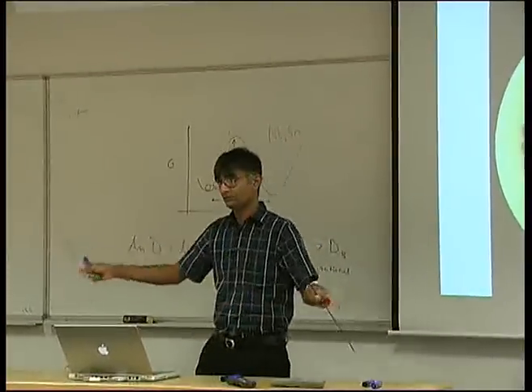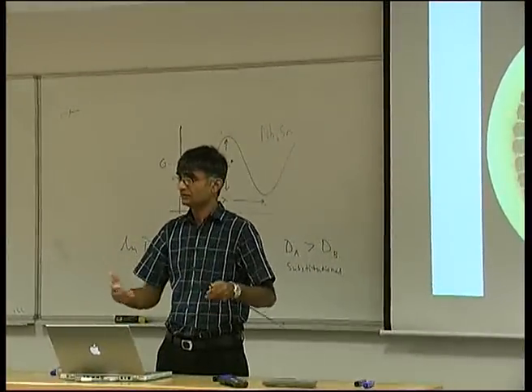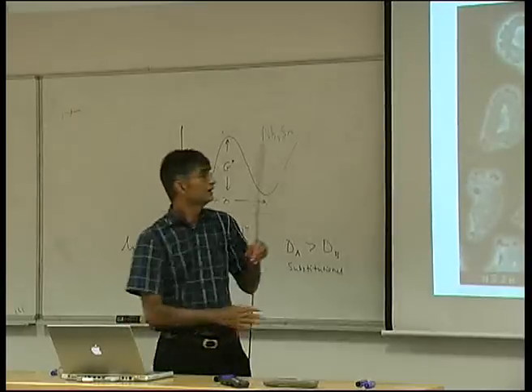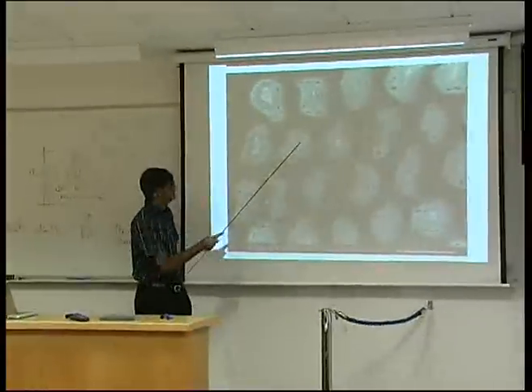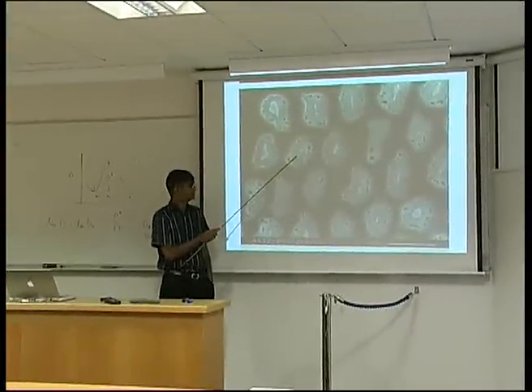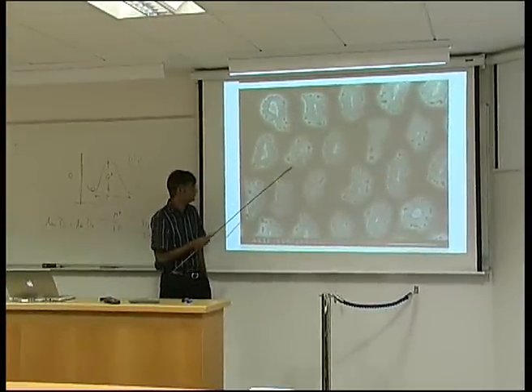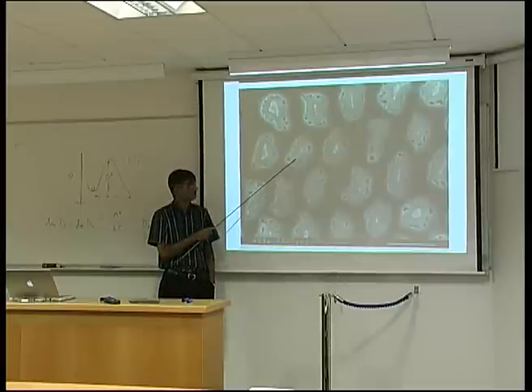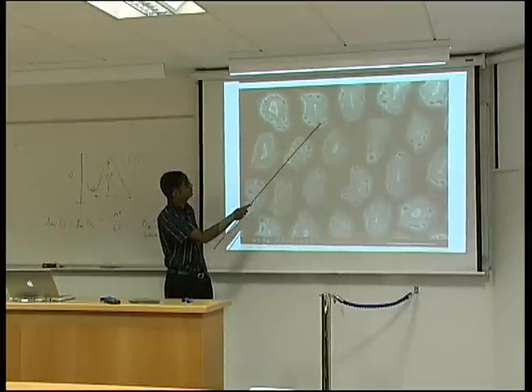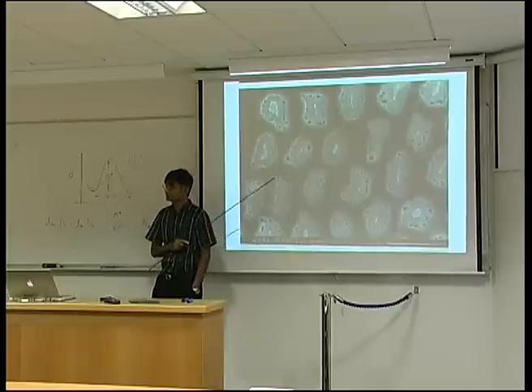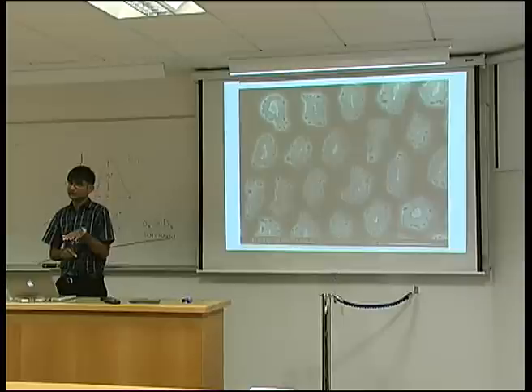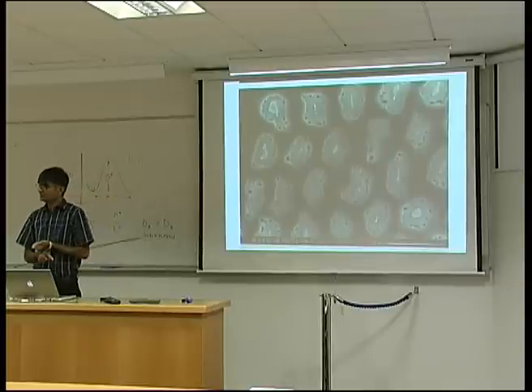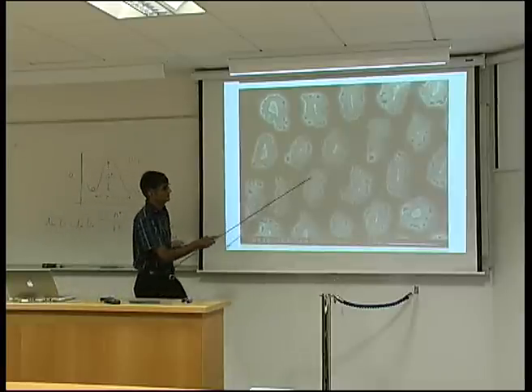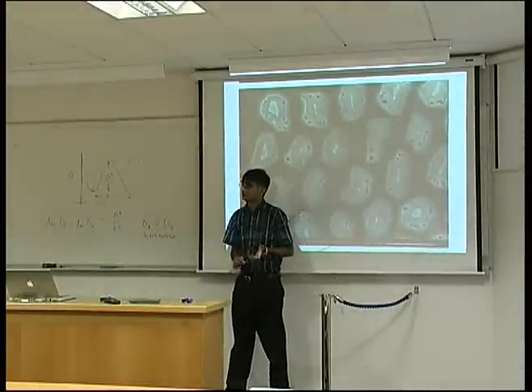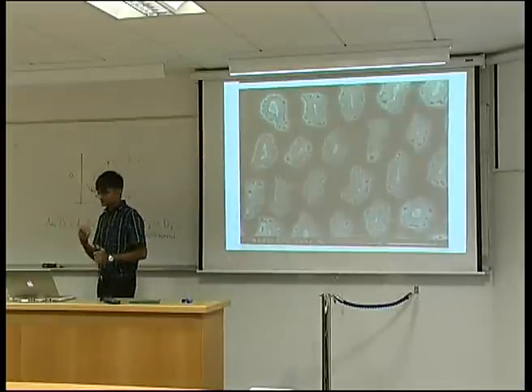So after you've made it into the form of wires, you heat treat it to allow diffusion to form this compound. And if you look very closely, this is now Nb3Sn. It's after the diffusion has happened, and tin from the bronze has diffused, combined with the niobium to form Nb3Sn, and you end up with porosity. And that is again Kirkendall porosity, because the diffusivity of tin in niobium is different from niobium in tin. So around every one of those filaments you find these holes. So this is a real effect, Kirkendall porosity.